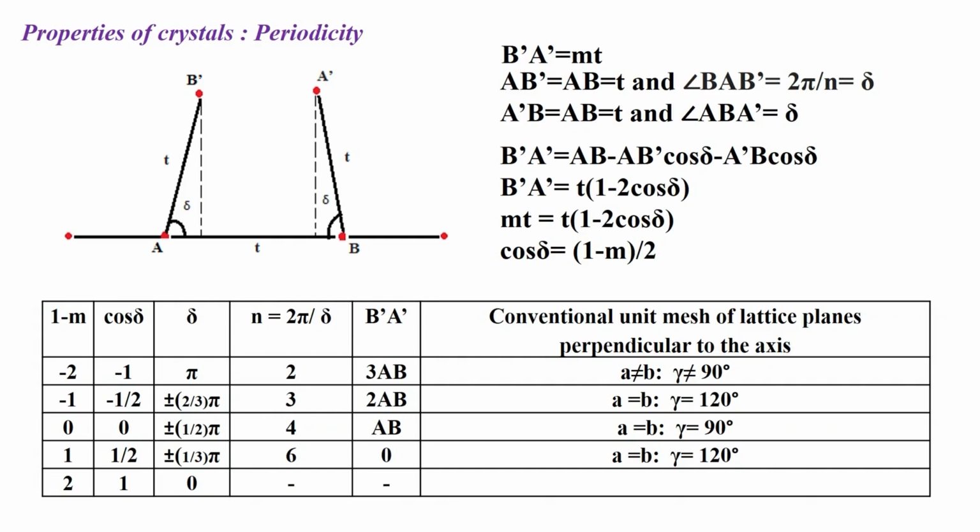We were going to talk about plane lattices. These now in fact define the plane lattices. These 1, 2, 3, 4 types of plane lattices we will get. In fact, we get a total of 5 plane lattices. We will discuss it when we bring in the discussion on different types of lattices that are possible in crystalline materials. At this juncture, in this particular slide what we are illustrating is that the number of rotation axes that are possible are restricted to 1, 2, 3, 4 and 6 in crystalline objects which have periodicity.